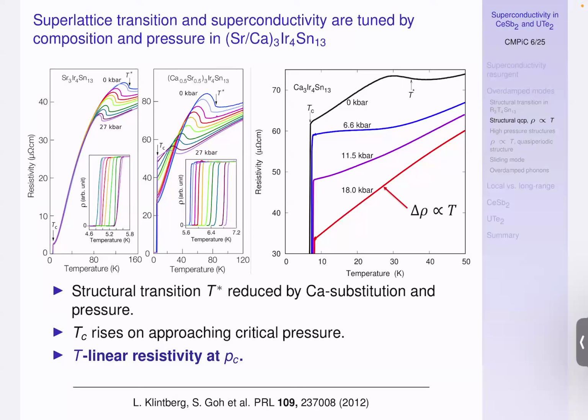So the initial, our collaborators in China, I'm afraid, was it Yang? Anyway, I can't remember the group who sent us the initial samples. They thought that this was, in fact, the spin density wave transition. But we became more and more convinced it's not. It's actually just structural. One aspect was the magnetic susceptibility decreased, which was plausibly explained by the reduction in the density of states, which happens when you gap out part of the Fermi surface as part of this decrease of the Brillouin zone. Is it commensurate? It's commensurate, like doubling. It's just exactly that.